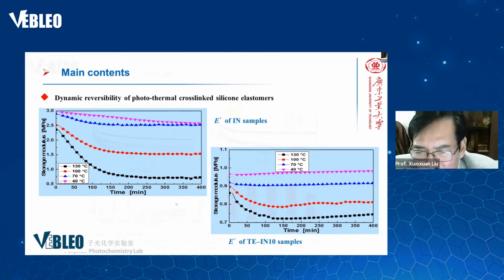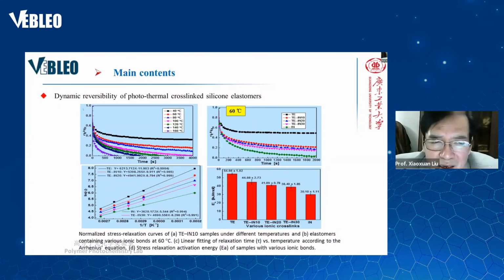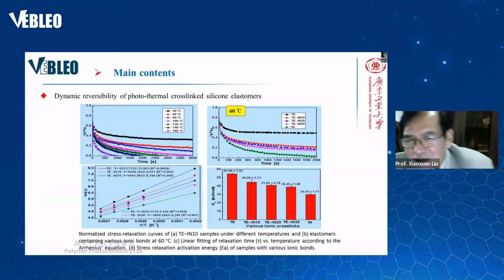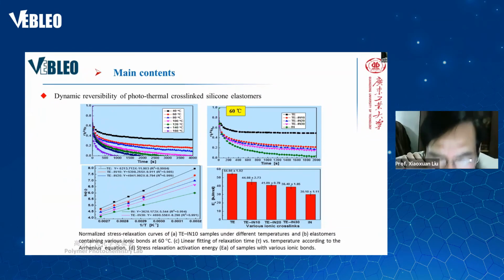Different modulus. And dynamic reversible photo cross-linking of the silicone elastomer. This is the normalized stress-relaxation curves of the TE-IN10 samples at different temperatures. It is figure A. B is the elastomer containing various ion bonds at 60 degrees centigrade.